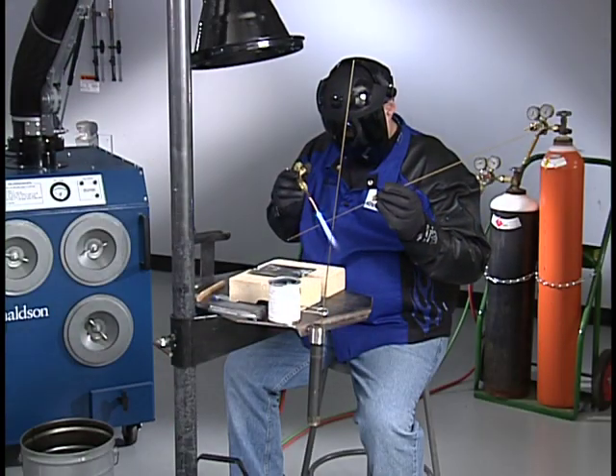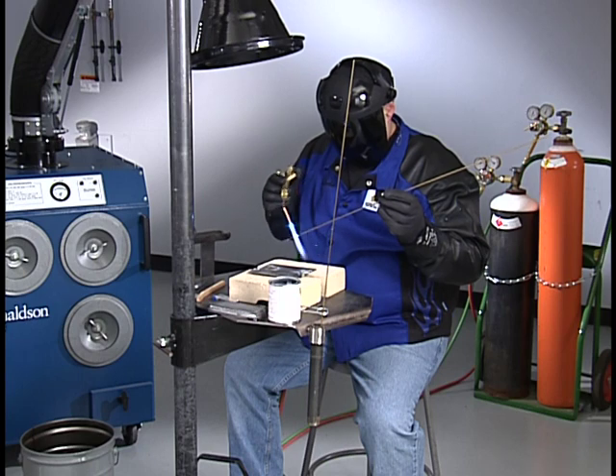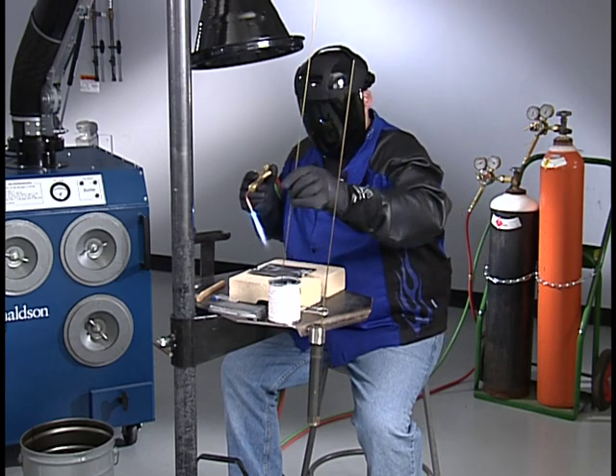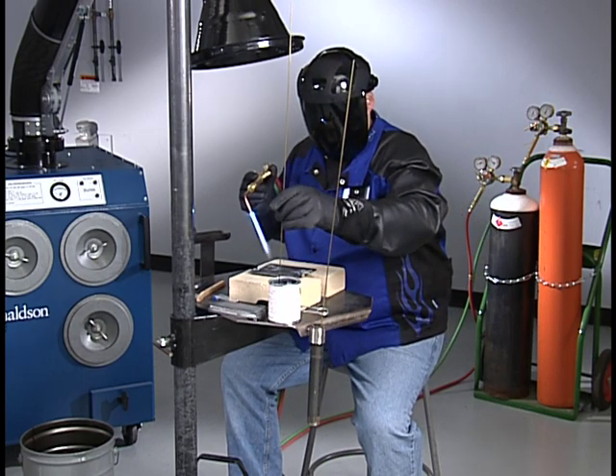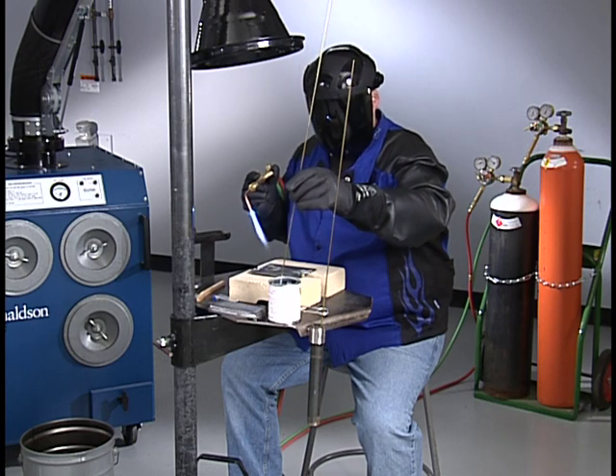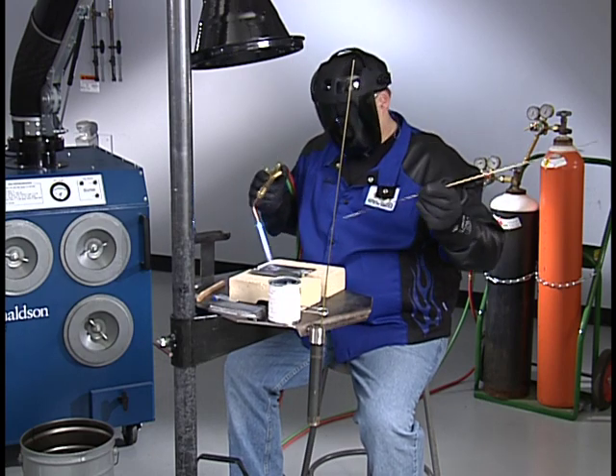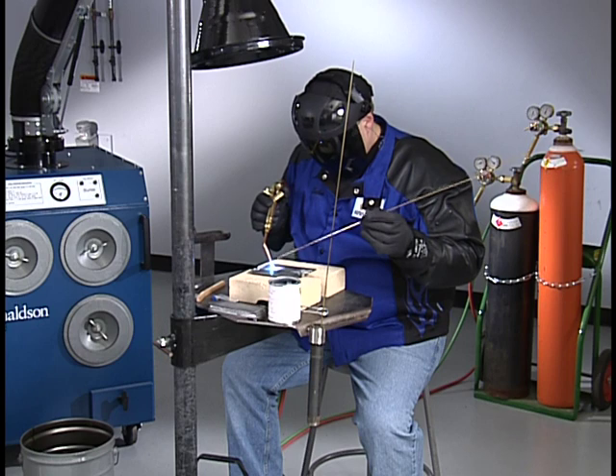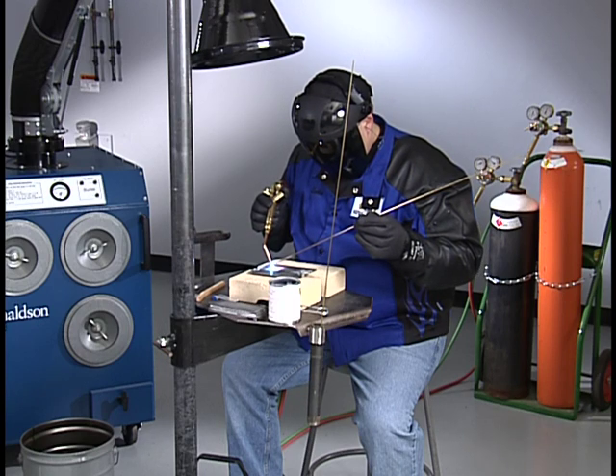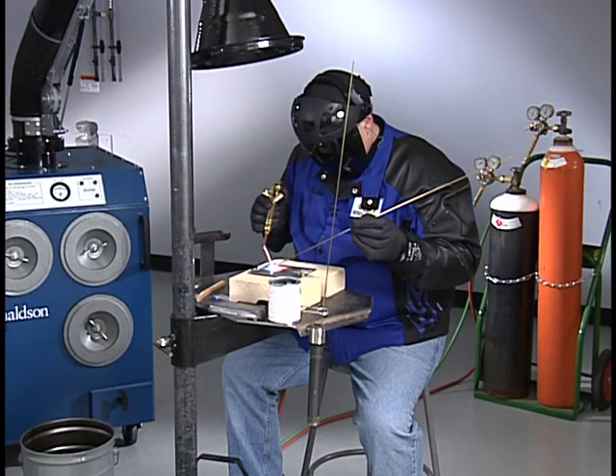Before restarting a braze weld, if you are using non-fluxed filler rods, always add flux to the brazing rod before you begin welding. To restart, position the flame at the back of the weld crater and gradually heat the weld to create a puddle. Once the puddle is formed, move forward, then begin to add filler metal and continue welding.